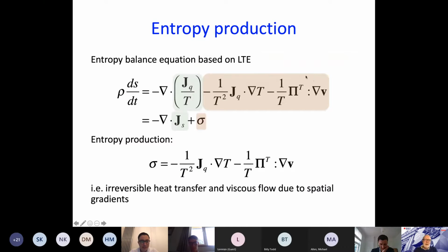And we can describe that system by looking at the entropy production, because we can think about it from the point of view of non-equilibrium thermodynamics. And based on the ideas of local thermodynamic equilibrium, we can write down an entropy balance equation where we have, in the green there, the entropy flux, and in the other colour, which I really don't have a word for, beige or something, the entropy production. And the entropy production, you can see, consists of two terms for a single component system. We've got a term that's proportional to the temperature gradient and the heat flux, so it's bilinear in the flux and the field, or the thermodynamic driving force. So that's the entropy production due to heat flow. And then we have another term which is the entropy production due to the deformation of the material. So that's the viscous flow term in the entropy production.